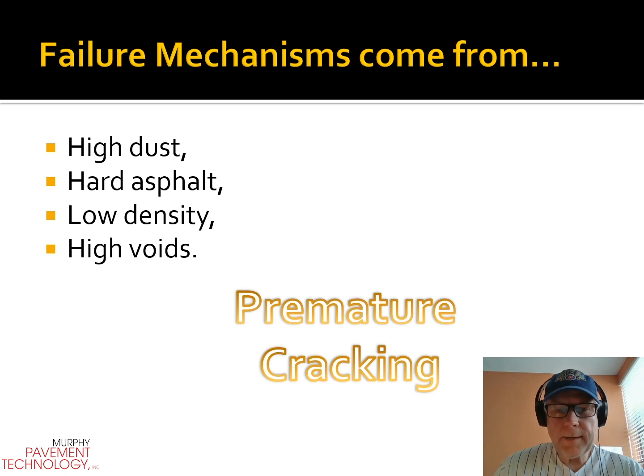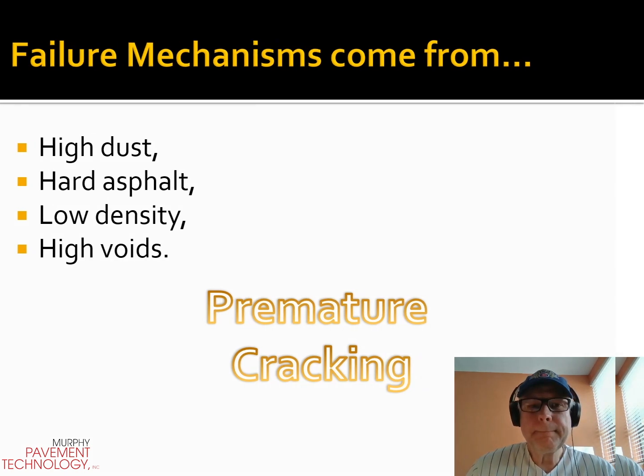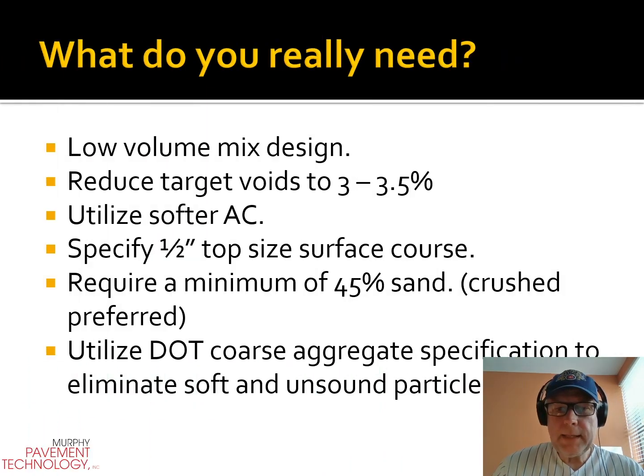All of the other items can cause premature cracking. Premature cracking leads to moisture. Moisture leads to failure. So what do you really need? You need a low volume mix. You need to reduce air void content. Use a softer asphalt. Specify a 1/2 inch maximum particle size for your surface course. Use a minimum of 45% sand. Crushed is preferred. And then specify DOT coarse aggregate specifications. Eliminate soft and unsound, and do not use anything that rusts.